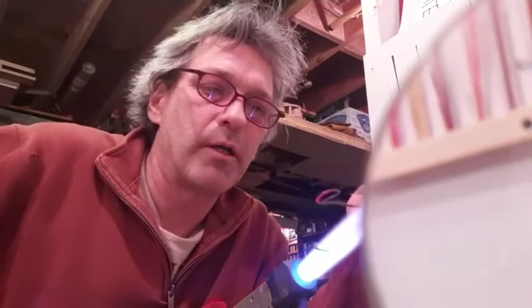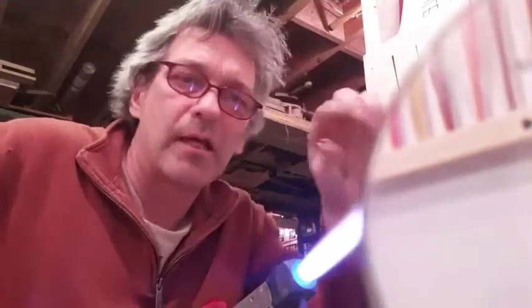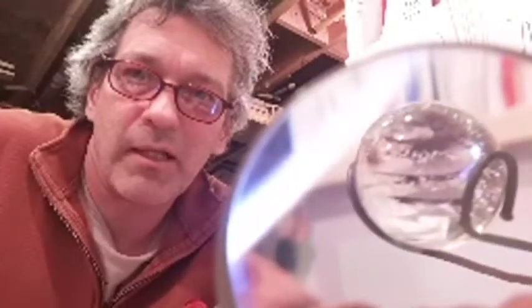And now I'm going to pick up the marble out of that fireproof compressed ceramic fiber board with this marble pliers. This is a wire tweezer that I made. I heat it up till it's orange and let it just turn black, and that's the right temperature for touching the glass without shocking it. There's our marble. Now we'll put it in the annealing oven.